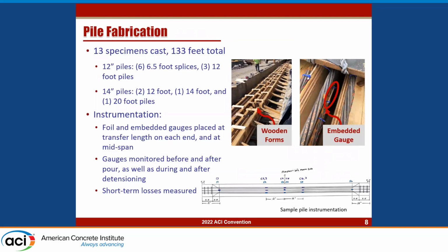With the sections finalized, pile fabrication began. We cast 13 total specimens with lengths ranging from 6.5 feet to 20 feet. Prior to casting, foil and embedded gauges were placed at several locations, specifically at the transfer length locations, as well as other critical locations depending on the specimen. For our flexural testing, most of those were around mid-span where we'd see the highest moments. These gauges were monitored both before and after pouring, as well as during detensioning, so that we could get an idea of what kind of short-term losses we're seeing in these piles.